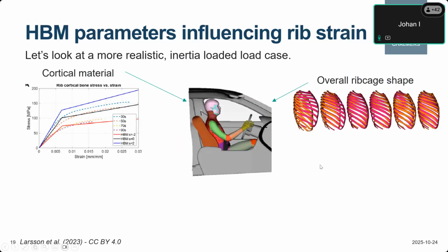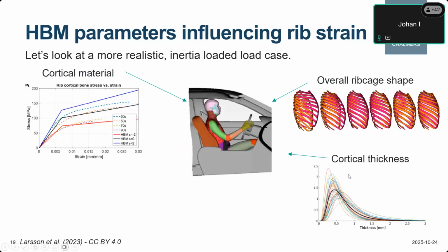We also varied the cortical material according to a realistic range. So all this variation is based on population data. We are varying it according to plus minus 1 or 2 standard deviations. I don't remember what we used. It's actually 2 standard deviations as in the population. So we vary the material parameters in the cortical bone. We vary the cortical thickness. So what you see here is the distribution. These are different human body models with different distributions of the cortical thickness. We have a cortical thickness going from 0.1 up to 3 millimeters, but it varies in all the different human body models here. We vary the rib cross-section,